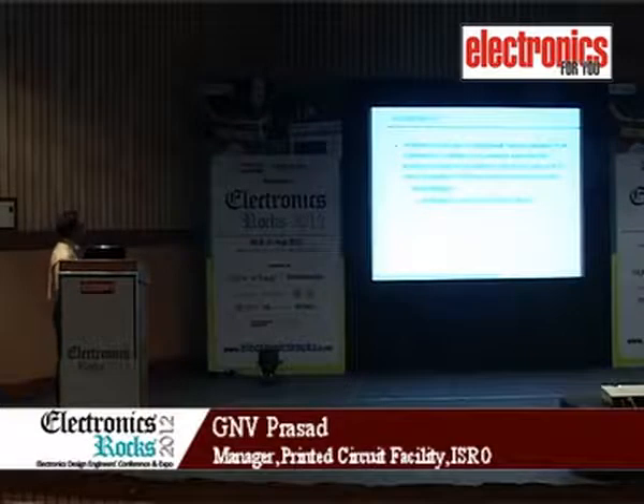And we do a solderability test. Finally, once the PCB is there, components have to be soldered, and we have to verify whether it takes the solder, because that is critical: solder joints have to be intact for reliable performance of the electronic package. So it should have a minimum 95% wetting on the surface. I will be showing some photographs of good wetting, non-wetting and de-wetting.